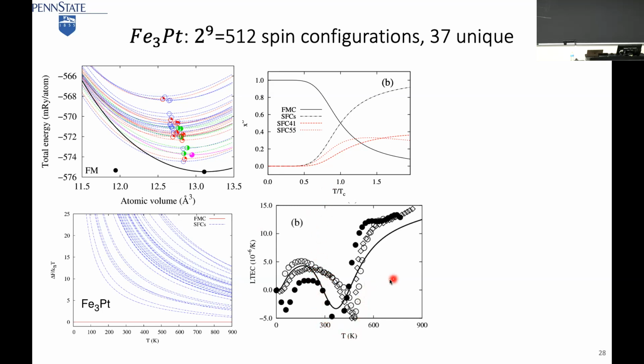We come back. So why would the volume decrease at that time? Look at this one. All the metastable ones have a smaller volume, right? The ones that have larger volume, right? So all the replacements have smaller volume. So everybody will have volume increase, but the replacement rate is larger than the volume increase rate, so the total volume can decrease. So it's nothing strange. Actually, nothing wrong about these soft modes. It's basically replacement. It's a number game.